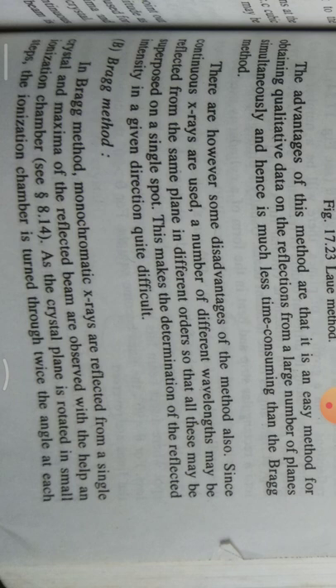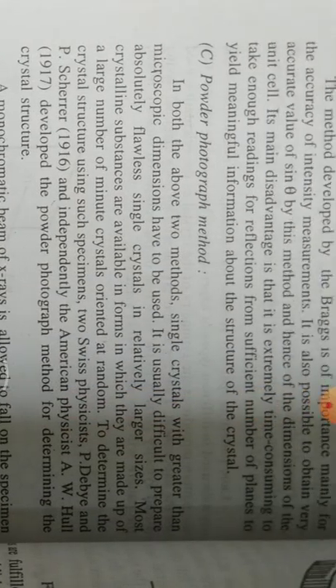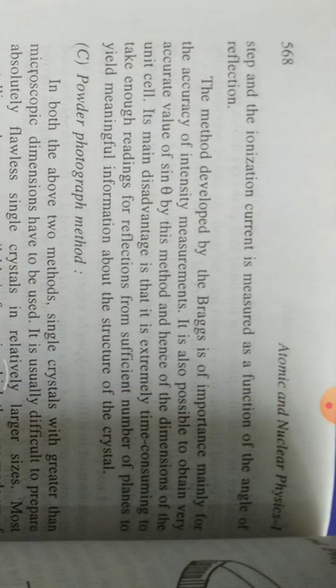Next, Bragg's method. In Bragg's method, monochromatic X-rays are reflected from a single crystal and maxima of the reflected beam are observed with the help of an ionization chamber. As the crystal plane is rotated in small steps, the ionization chamber is turned through twice the angle at each step, and the ionization current is measured as a function of the angle of reflection.